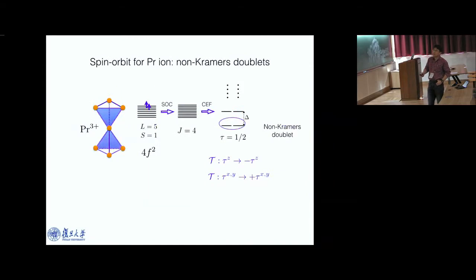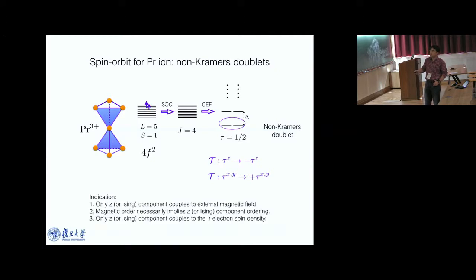This guy is a non-Kramers doublet. You have two f electrons, and the spin and orbit are entangled for this J equal to 4. And under the crystal field, you get a so-called non-Kramers doublet, and it has a special property under time reversal. Only the Ising component, the local Z component, is magnetic, and only the Z component would couple to the magnetic field, and also couple to the conducting electron spin density.